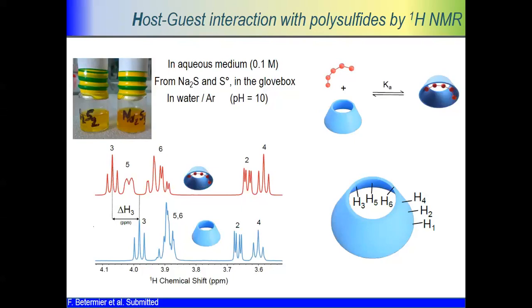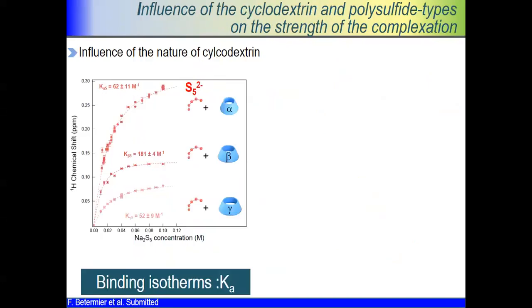So this is a clear indication that the polysulfides are not going around cyclodextrin, but inside. So then we really need to understand more about this type of interaction, and we look if we can define and compare what will happen depending on the type of cyclodextrin, which are alpha, beta, and gamma. As I mentioned to you before, they depend on the size and so on.